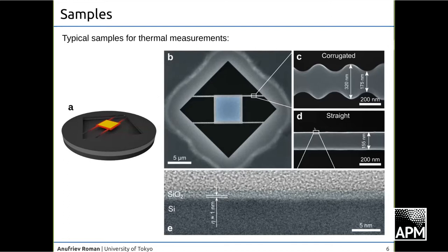This is top view. And if we look with the transmission electron microscope on the edge of this nanowire, we will see that the roughness of this structure is about the atomic lattice. If you have a good monitor, you can see the atomic lattices here. So our nanowire is pretty smooth. I mean, on top and bottom, it's a polished wafer, so it's totally flat. And the RIE allows us to fabricate rather smooth nanowires still.